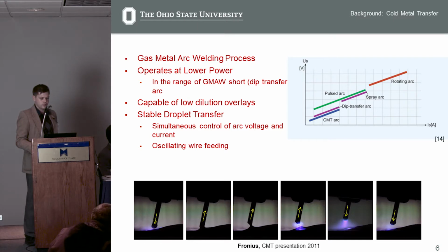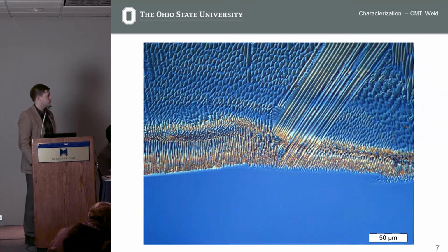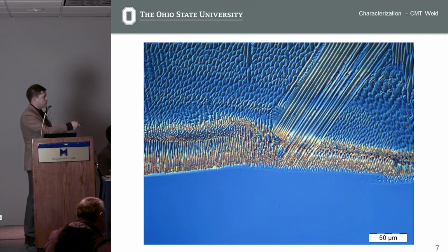These first two slides are meant to compare the cold metal transfer weld fusion boundary. Here we see the 304L base metal being welded on top of with 52M, and there's a columnar and subsequent columnar dendritic regions that transition into weld metal composition fairly quickly. And in fact, in the previous study, we measured the transition region of this weld zone to be on the order of a few tens of micrometers, so around 20 micrometers wide.